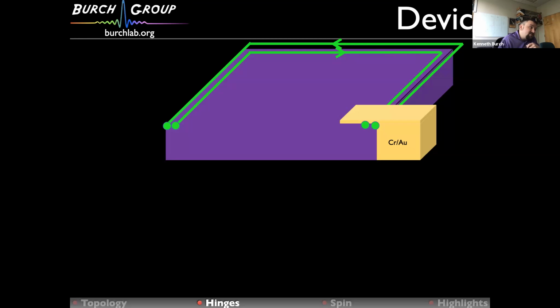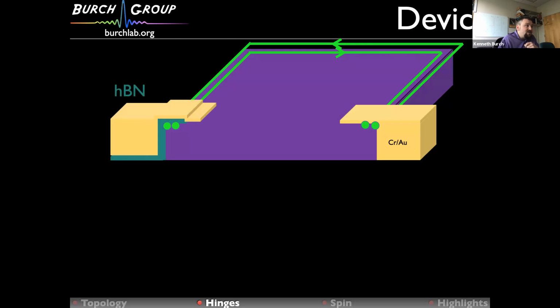But to prove to ourselves that it wasn't a bulk effect, we would then put HBN over an otherwise identical contact, right? So this HBN would basically insulate our other contacts from touching the hinge, and so they would only touch the bulk. And so we would have a built-in control. So we could see if we were seeing enhanced density of states from the hinge, or if we're seeing it from the bulk response.